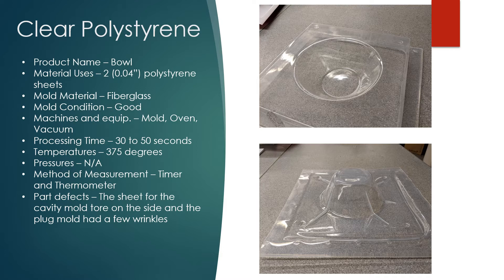As far as defects go, the sheet for the cavity mold tore on the side because of the height of the mold, and the plug mold just had a few wrinkles.